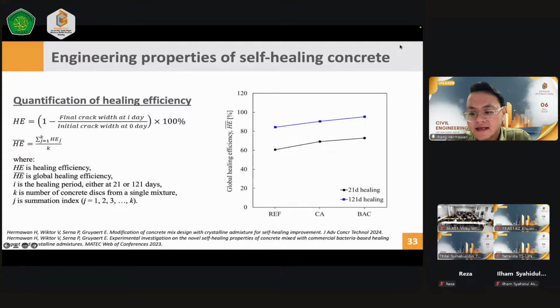Then on the picture on the right hand side, I compared the effectiveness of the crystalline admixture and also the bacteria. The reference will also promote the autogenous healing mechanism that I mentioned, which is why the healing efficiency reached around 60% in this case. But with the use of the crystalline admixture and the bacteria, the healing efficiency increases due to the autonomous healing mechanism. So this shows that the addition of the healing agent is also effective to promote a better healing process.